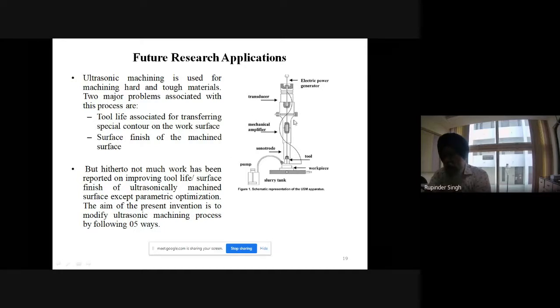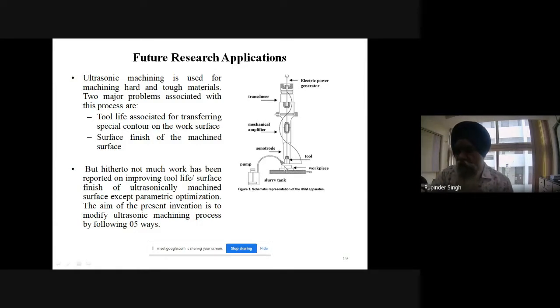At this location, I am putting a tool which has been fastened to this surface, right? So this tool is now vibrating at a frequency of 20 kilohertz, right? Now there is a workpiece over here, and there is a gap between the tool and the workpiece. What I am doing is putting the slurry in between the tool and the workpiece. Once the slurry particles, which comprise alumina or silicon carbide, come in contact with the tool, because the tool is vibrating at a high frequency of 20 kilohertz, their momentum is increased 2.5 lakh times. With that high momentum, they strike the workpiece, and we get erosion over the surface, right?